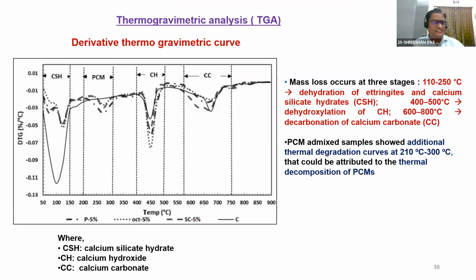So next is the TGA. I will just quickly go ahead. You can see this is not my TGA, this is my DTG, that is the derivative thermogravimetric curve. If you do the DTG, then only you can get this kind of peaks. Normally, if you see some of our papers, in a normal concrete, whatever is here is also there. There will be one peak, that is calcium silicate hydrate, a second peak, that is calcium hydroxide, and the third is calcium carbonate.